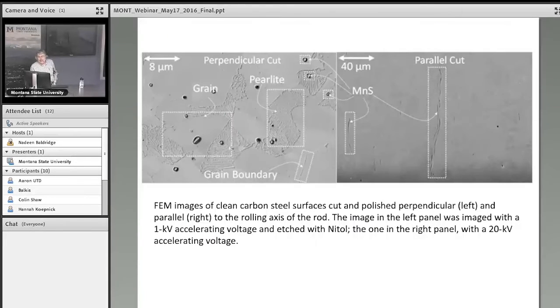Here is an example. You have a long bar, rolled through a mill. This is called the rolling direction. You can polish it perpendicular to it. That's the previous picture. I show another version of it here. You can see the tips of manganese sulfide inclusions, and then the pearlite and the iron grains.